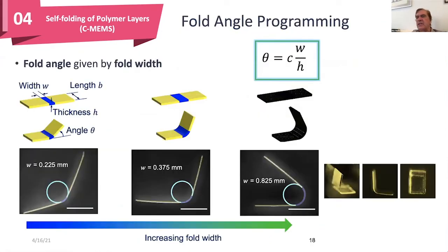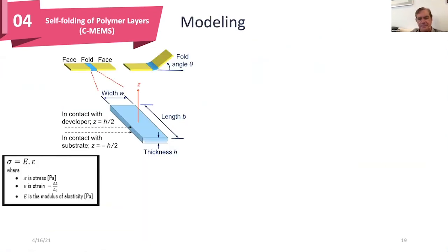I will not spend a lot of time on the modeling. That would take me easily another 20-25 minutes. But as I indicated, what are the variables we have to control this whole folding exercise? Well, we have the width of the fold area, we have the thickness of the film, and we have this length B here. And then this theta here is this folding angle. And that is basically what you put in your model.